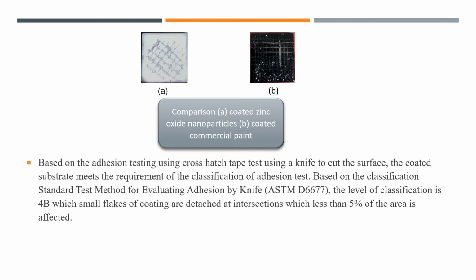The comparison of the coated zinc oxide nanoparticles and the coated commercial paint. Based on the adhesion testing using the cross-hatch tape test, using a knife to cut the surface, the coated substrate meets the requirement of the classification of adhesion test. Based on the classification standard test method for evaluating adhesion by knife, ASTM D6677, the level of classification is 4B, with small flakes of coating detached at intersections, where less than 5% of the area is affected.